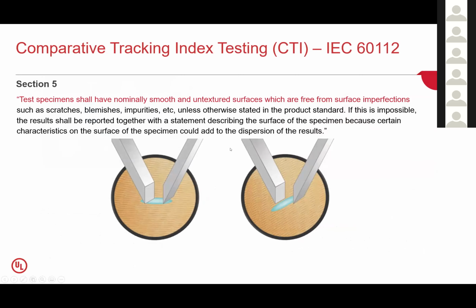So I'm going to jump to comparative tracking index. This is a test where the surface is being contaminated and we're looking for potential arcing to occur or tracking from one live element to another live element, or in this case, electrodes. Nominally, this test is conducted on a smooth surface that is free of surface imperfections. When we look at many of our 3D printing techniques, you have an inherent surface texture that is being put onto that material. How that surface texture can impact the results of this test come about by the liquid that is being dropped between these electrodes to create that tracking bridge.